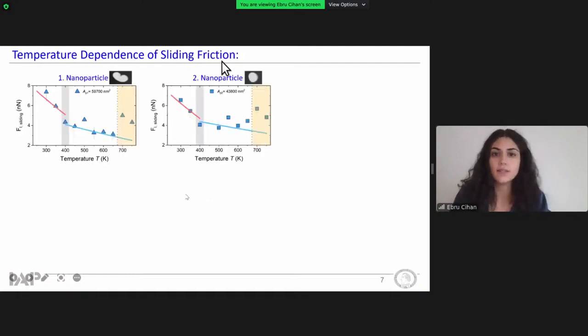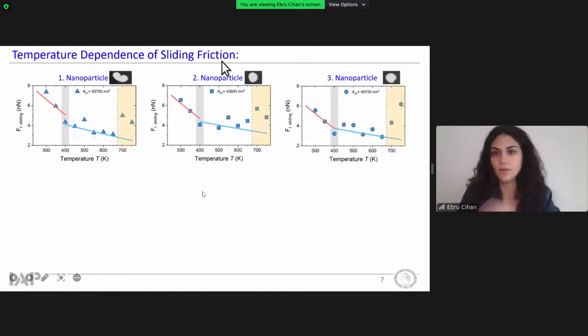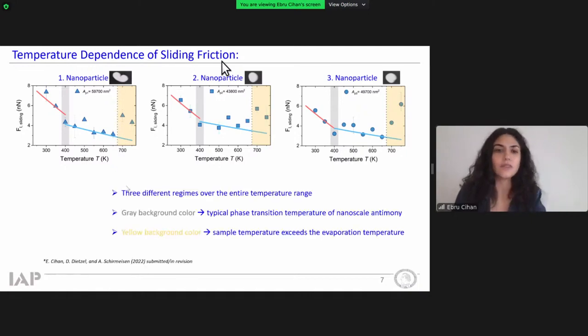So this process was first applied for 3 nanoparticles, and the following results were obtained. Accordingly, we can talk about 3 different regions for the specified temperature range. First, friction decreases with increasing temperature, and this decrease continues for a while, and then at even higher temperatures, it increases slightly, as shown in the yellow area here. Additionally, the gray background shows a typical phase transition temperature of nanoscale antimony, and the continuous lines marked in red and blue were calculated according to the thermally activated stick-slip Prandtl-Tomlinson model, and they reflect different energy values for the low and high temperature regions. Due to time constraints, I will not go into further details at this time.